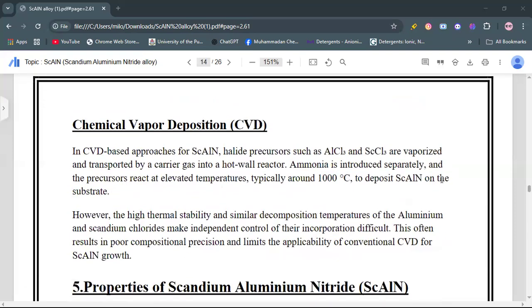The next is chemical vapor deposition. This is another approach to fabricate scandium aluminum nitride thin films. In this, halide precursors such as aluminum trichloride and scandium trichloride are vaporized and transported by the carrier gas into the hot wall reactor. Ammonia is introduced separately as a nitrogen source, and the precursors react at elevated temperature, typically around 1000 degrees Celsius, to deposit scandium aluminum nitride on the substrate. However, high thermal stability and similar decomposition temperatures of the aluminum and scandium chlorides make independent control of their incorporation difficult. This often results in poor compositional precision and limits the applicability of conventional CVD for scandium aluminum nitride growth.